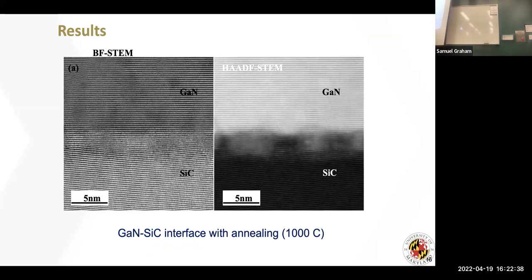What's interesting, and because of time, I'm not going to show you, is that if you do a chemical map, you'll see that you have argon trapped in these little spots at the interface. We're not really sure what this trapped gas does when we do the measurements. It's there. When we start looking at more of the science of this, should we use a different molecule? You'll see why I'm mentioning that a little bit later, because these molecules can potentially help aid the heat transfer across these interfaces.